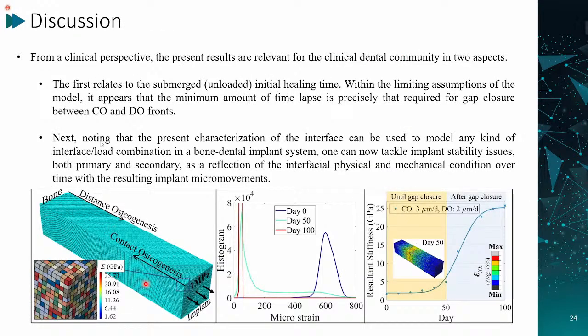So from a clinical perspective, the present results are relevant for the clinical dental communities in two aspects. The first relates to the minimal initial healing time. Within the limiting assumptions of the model, it appears that the minimum healing time is precisely that required for gap closure between the CO and the DO fronts. So the next, noting that the present characterization of the interface can be used to model any kind of interface and load combination in a bone dental implant system. So one can now tackle implant stability issues, both primary and secondary, and also as a reflection of the interfacial physics and the mechanical conditions over time with the resulting implant micromovements.